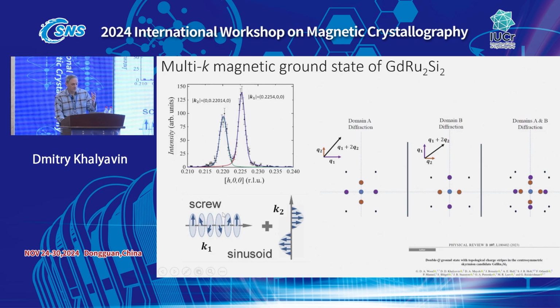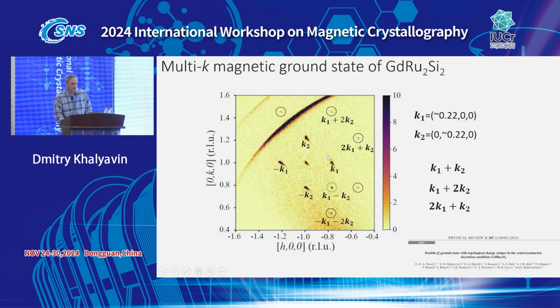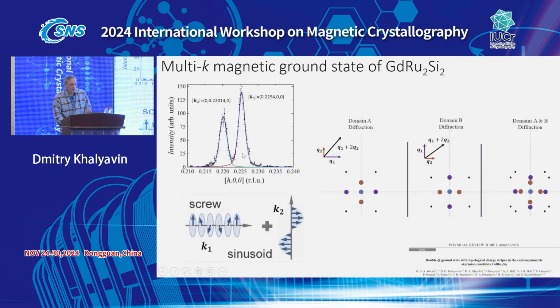And based on all that information, so why is it split? Because we have domains. Since they are not equivalent, the four-fold symmetry is lost, and these arms are no longer required to be the same, they are different, and on top of that we will also have domains. So on one shot, on one spot, we have a superposition of two domains. That's why we see two peaks.